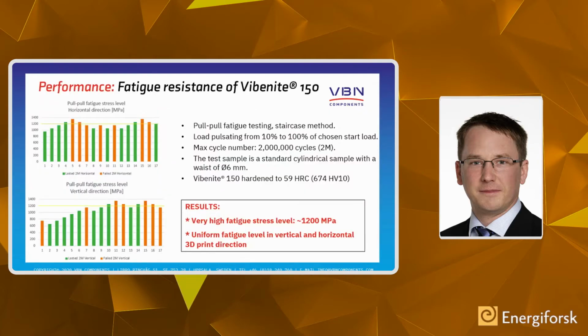And just to show you one thing, very technically, one of the fatigue measurements we have done on the Vibenite 150. We have pull-pull fatigue testing, staircase method. Then we have a fatigue stress level of about 1200 megapascals. And it's also uniform if you print standing test bars or lying horizontal test bars. You have the same fatigue stress level. This is an indication of a very good process to manufacture these materials. And what I heard, this is about twice what you can find in other additive manufacturing today.